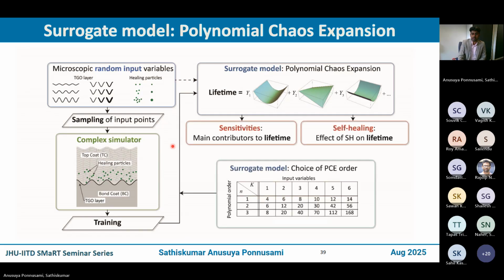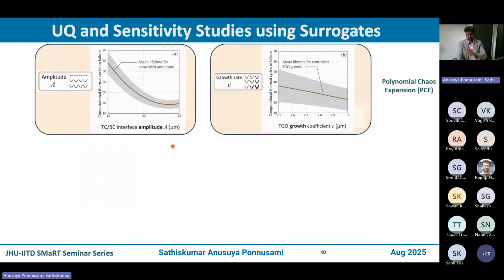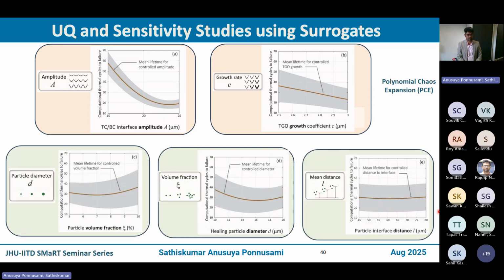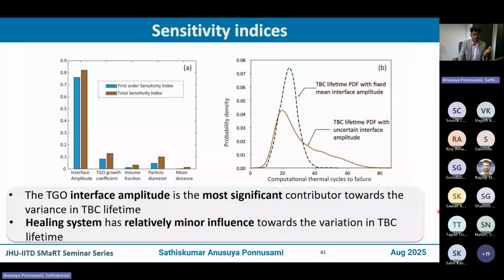So without getting into the details, let us get into the results. These are the quantification of the sensitivity of different parameters, or in other words, the results of the PCE surrogate model for 5 different parameters. This was a useful result for material scientists. Why? Because you have 5 parameters that they think are really important, but by looking at it, you see only the top 2 parameters are quite sensitive to the lifetime, whereas the bottom 3 are not as sensitive as the top 2. And that in itself is a practically useful and valuable result that computational scientists can feed to the material scientist.